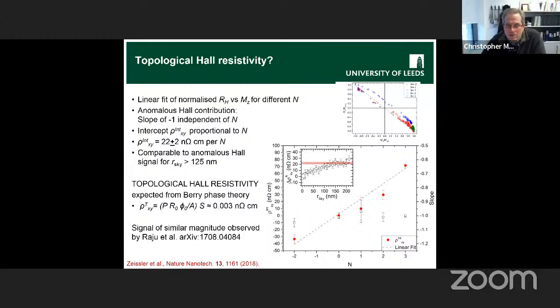So these red lines are the important ones. We've got 0, 1, 2, 3, -2 of these Skyrmion objects, and you get a reasonable straight line fit through that. It tells you you're getting about 22 nano-ohm centimeters for every Skyrmion object you've got in your disk. Now, if you use that Berry phase theory and try and calculate what you'd expect, you would find that it was about 1,000 times smaller.